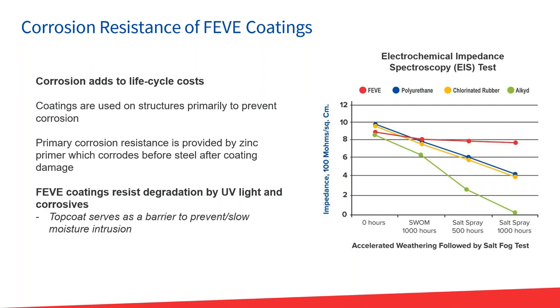Then you expose it to an artificial weathering test, that sunshine weatherometer, for 1,000 hours. So you start that degradation process. Then you can see how it responds to a salt spray test, and we did it at 500 hours and 1,000 hours. What you're seeing is as these coatings degrade from UV light, and then have that exposure to salt, because that UV light has started that microcracking phenomenon that I mentioned, salt intrusion starts to happen. And of course, if you have salty water going through your film, now you can send electricity through it. That's essentially what we're seeing here. What you'll note is that red line with FEVE stays pretty steady and stable. That just means it's not degrading significantly from the sunshine weatherometer test, so it's acting as a barrier longer. That's really the key to how these materials can provide corrosion resistance.